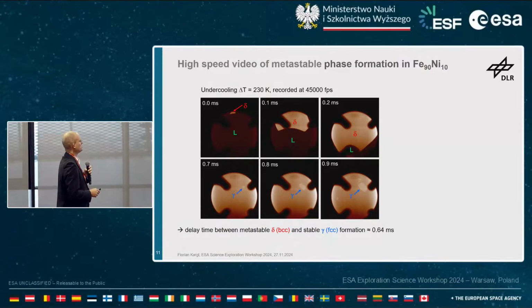So the experiment looks slightly different. So you see again, this is an undercooled iron nickel sample in this case, very deep undercooling, 230 Kelvin below the liquidus of the stable phase. And what you see here is the undercooled sample, so barely noticeable, quite dark actually. And then you see this bright spot up here. And the bright spot up here is related to the growth of the metastable phase. So for this deep undercooling, the metastable phase in this case forms first, the BCC phase, and then this continues to grow. So you see it's spreading over time, very high velocity here. So we have very short recording time, 45 kilohertz in the high-speed camera. And then at a certain point in time, you see another bright spot appearing here. And this is the growth of the stable phase that comes after the metastable.